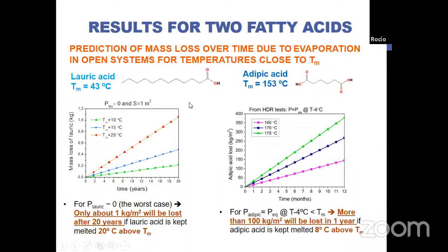We can say that only about 1 kilogram per square meter will be lost after 20 years. Look at this scale, it's years, and these are mass loss. If this material is kept 20 degrees above melting temperature, but if we go to the adipic acid, which is melting at 153, in this case, even if we assume that the adipic partial pressure in the vapor phase is just a little bit above or a little bit below the constant pressure, the equilibrium pressure at the melting temperature, we would lose more than 100 kilograms per square meter only after 1 year.